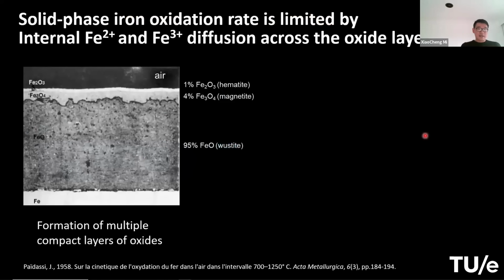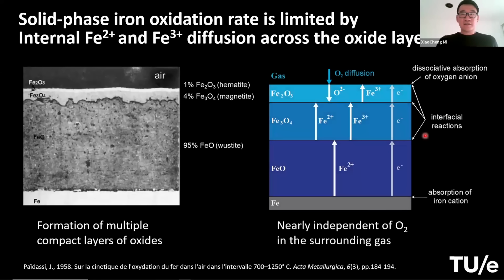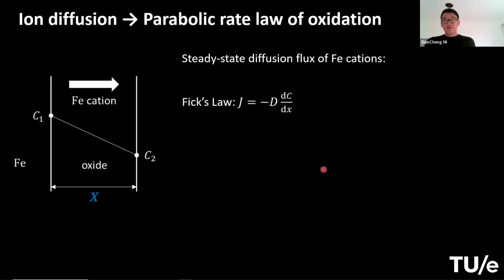And because of this multi-layer formation of iron oxide, its growth rate actually depends on the iron ion diffusion rate through the oxide layer. So how fast it grows depends on how fast iron ions, Fe2+ or Fe3+, transport across these 2 thicker layers. Of course, the thickest or most dominating one is the FeO layer. Okay, so if this internal diffusion is the rate limiting mechanism, then we can come up with a reaction rate model to describe it.